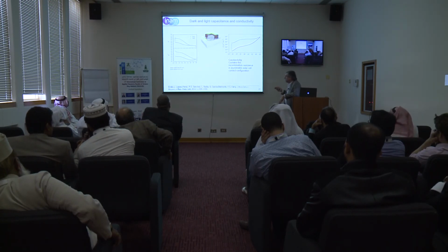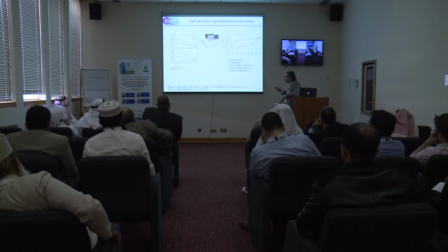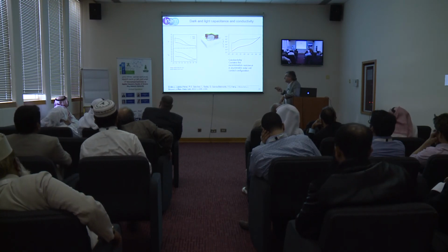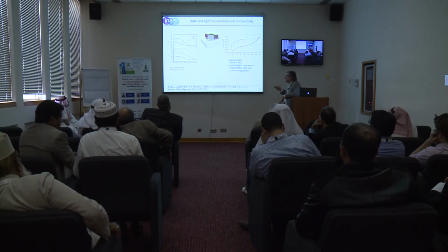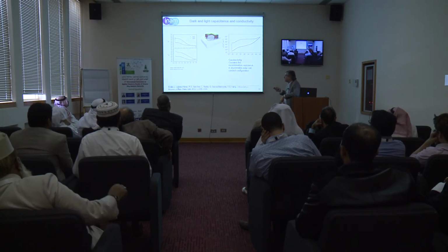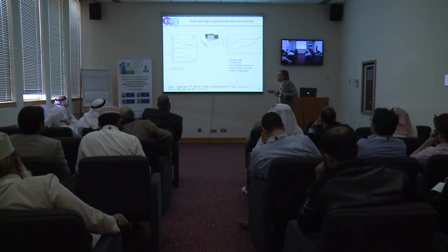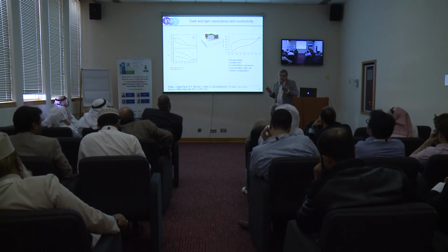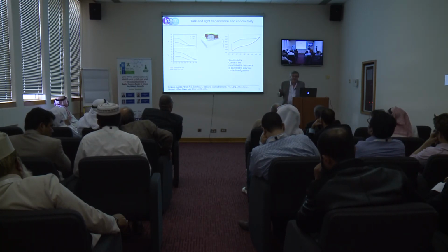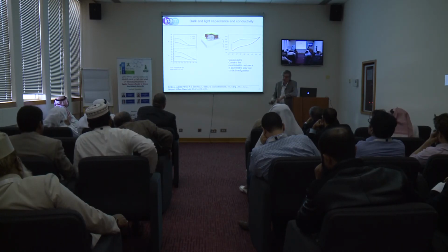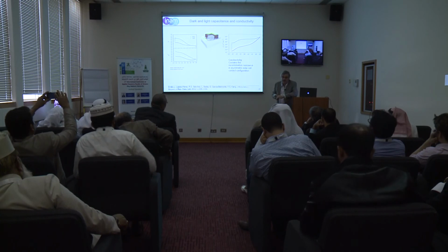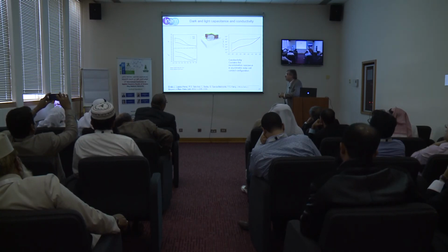So this is one first characteristic. As I said before, this is the capacitance as a function of frequency. This is the measurement in dark, and this is the measurement in light. So in dark, we have an effective dielectric constant of 1000. You can say, okay, it's a perovskite, maybe the epsilon is very large. But then you put light, and it goes a factor 1000 bigger. So this we need to explain.